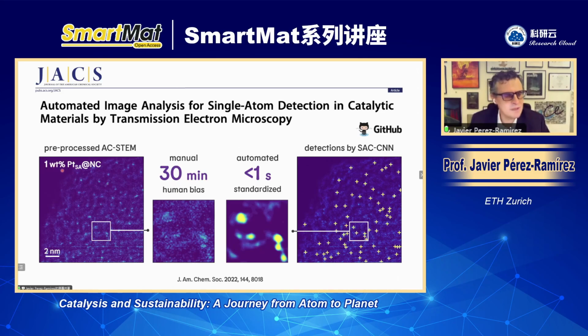You can see here 1% platinum single atom catalyst stabilized on nitrogen doped carbon. And that's a pre-processed image. This is an aberration corrected scanning transmission electron micrograph. Now, the point is that if I have a robot to prepare hundreds of samples, even in one day, how can I standardize the characterization of those samples that I would need to confirm whether I have succeeded with my synthesis or not? And of course, this poses big issues, right?